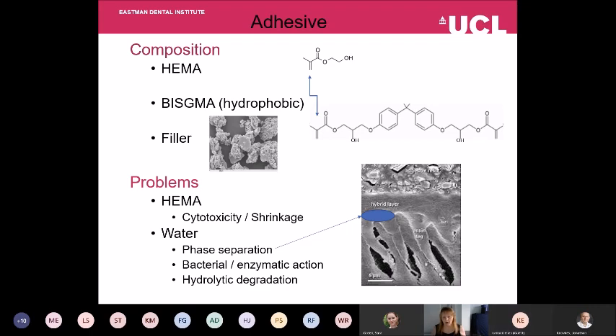After applying the primer, you have the adhesive. The adhesive often also contains HEMA, but what we do is to replace the aqueous phase, the water and the ethanol, with components that you would find in the dental composite. This includes components like bis-GMA, which is a large dimethacrylate monomer, and varying levels of different filler particles.